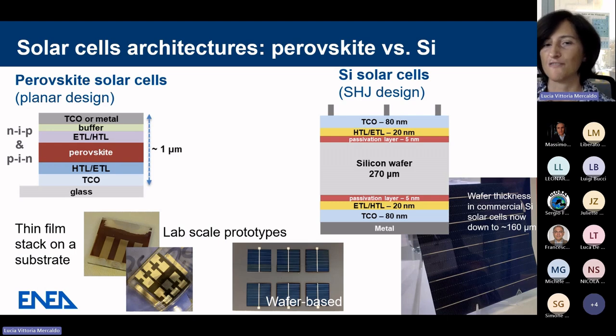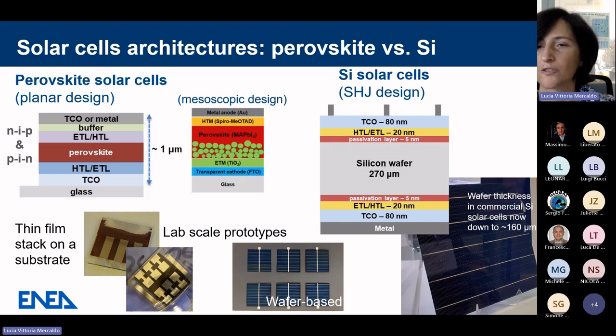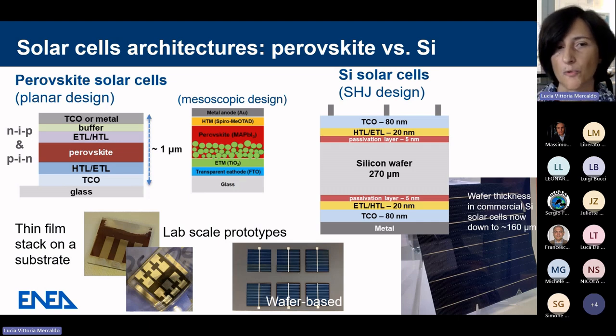But one main difference we already can see here is the thickness of these solar cells. In case of silicon, it is a rather thick structure. It's based on a wafer with, let's say, now it's getting around 150 microns thick in the commercial designs. While with the perovskite solar cells, we are talking about thin film architectures. So we have thin film stacks on a substrate. But just for completeness, I want to mention that there are also mesoscopic designs, which I will not discuss here, as we stick with the planar design in our activities.